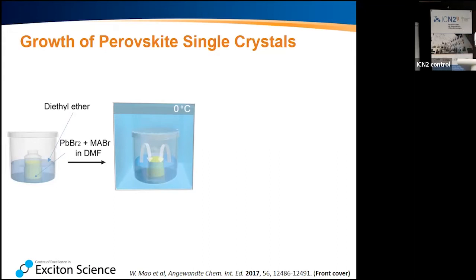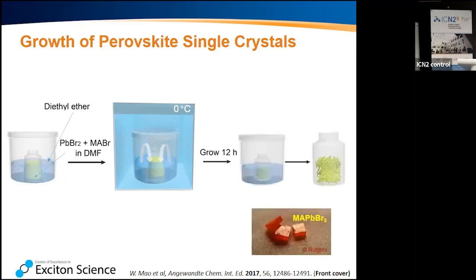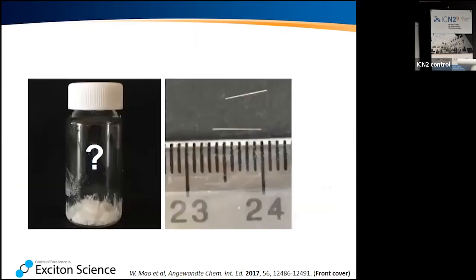Now, Wen-Chin thought, oh, I'll do even better than everyone else, and I'm going to put this whole thing into the fridge. So he did it at around 0 to 4 degrees Celsius. And surprisingly, we didn't get the orange crystals that we expected, the methylammonium lead bromide in this particular case, but we got some white material. And this slide here shows you again. So we got this stuff. Any ideas from the audience of why we got this and what it is?